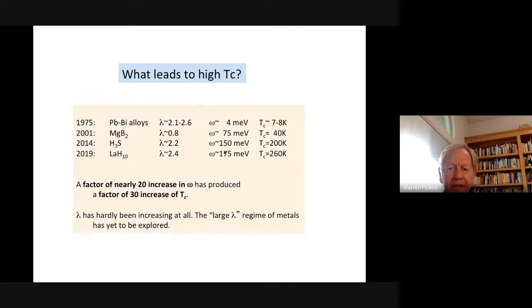Well, what has been happening, I've shown here. What leads to high TC? So 1975, the largest lambda materials were not the highest TC, but lead bismuth alloys, or maybe thallium in there too, all beside each other in the periodic table. These are very heavy atoms. Lambda's up to 2.5. The frequency measures about 4 millielectron volts, very low, and TC in those materials were 7 to 8 Kelvin.